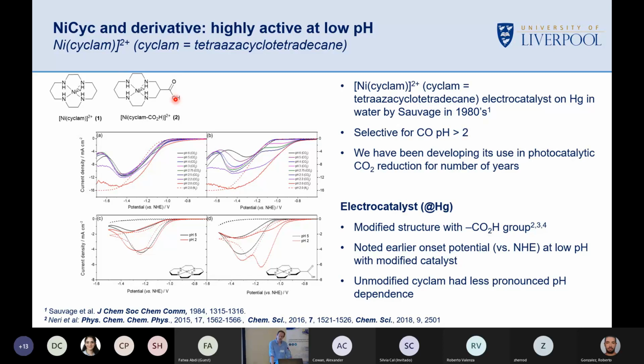Sorry. Okay, I thought you were saying 5 minutes, so that's fine. We can get very good selectivities for CO2 reduction. We get about 9:1 CO to hydrogen at pH 2. That's on a mercury pool electrode, which is rather fantastic. So we were delighted with this when we developed it, and I remember now the battles we had with reviewers, them saying, well, it works in acid, why do I care? You need to care. And they were going, no one's ever going to do CO2 reduction in an acid. It's very satisfying now to see the literature. That's my smug moment.